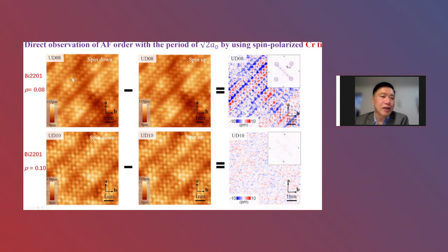You can see we use a spin down and a spin up to measure this topography. We subtract. Then we can see this kind of blue and red, which shows the intensity of this subtraction. You can see that it is the anti-ferromagnetic order clearly visualized by the spin polarized data. Doing Fourier transform, you can clearly see the anti-ferromagnetic order.